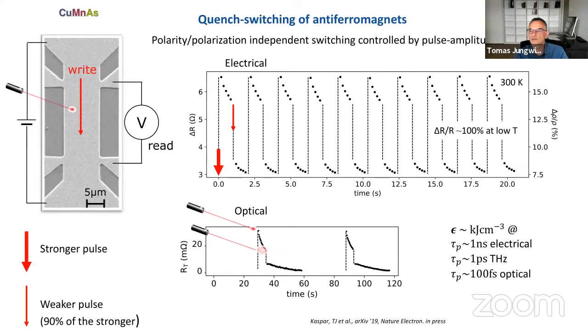So we can quench our system into a resistivity state which has resistivity twice as large as the residual resistivity of the film in the large domain state. So this seems to be one way to get around one of the problems of working with thin films, and that's the small readout signals. Here we see that we can have readout signals of the GMR or even reaching the TMR amplitudes.